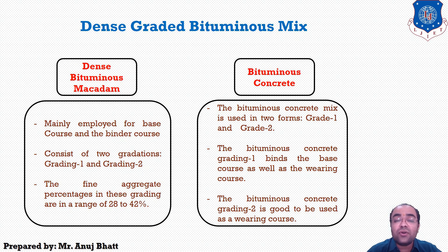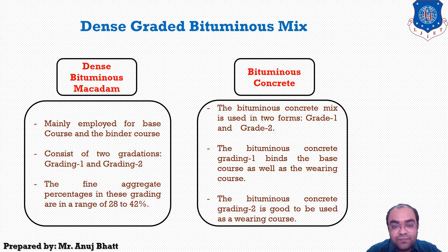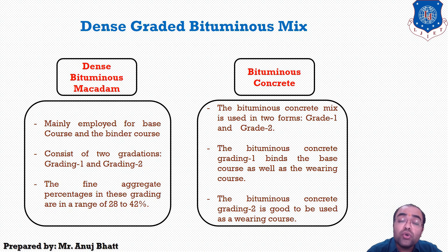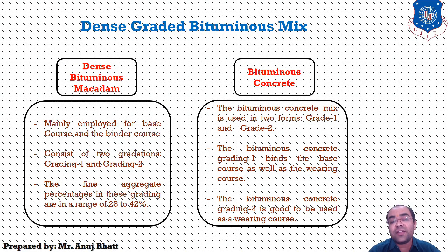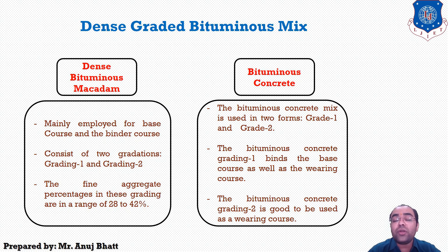The main criteria differentiating the grades is that Grade 1 consists of larger size particles and Grade 2 consists of smaller size particles. Grade 1 with nominal size of 37.5 mm has many disadvantages like segregation, which will later result in honeycombing. At lower air void levels this mix becomes permeable compared to Grade 2 DBM, causing problems related to water exposure. With increasing nominal size, permeability increases manifold.